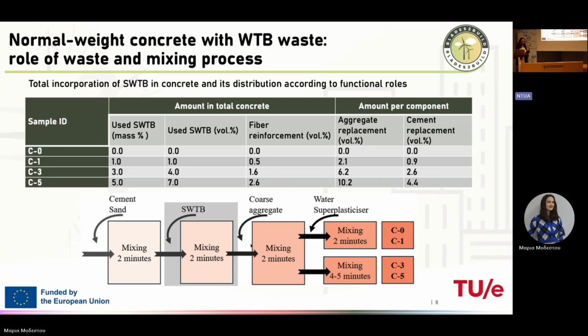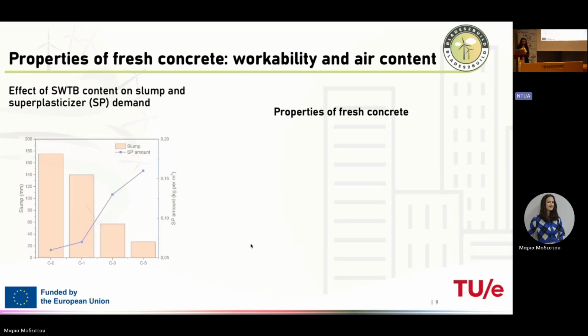Here is the process of mixing, because we mixed dry components. We tried different approaches, since it's challenging to make the mixture homogeneous. So we initially added cement and sand, then we added wind turbine blade waste to mix it with finer components, then we added coarse aggregate, and then we added water and superplasticizer. The higher the percentage of wind turbine blade waste, the longer the mixing duration, because it was challenging to make it more or less homogeneous.